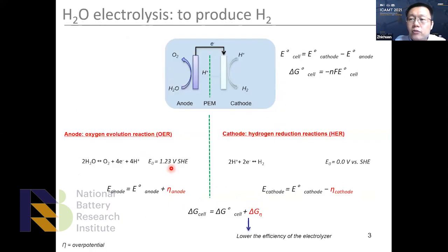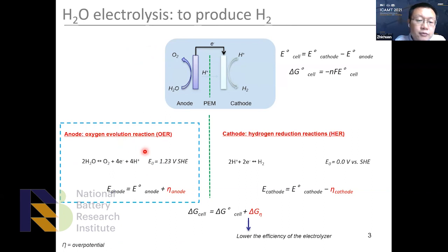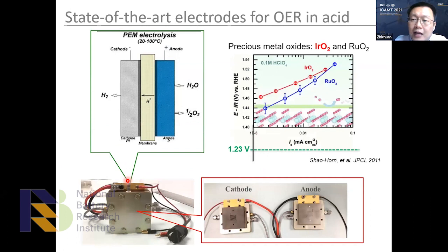For this overall technique, to produce the hydrogen, we have many ways, but water splitting is the most sustainable, of course, if we use the electricity from a sustainable resource. The bottleneck for hydrogen electrolysis from water splitting is the oxygen evolution reaction side. Although our target is hydrogen, the major energy loss actually happens on the other side, that is the oxygen evolution reaction. So the overall efficiency can be limited quite a lot by this very slow oxygen evolution reaction kinetics.